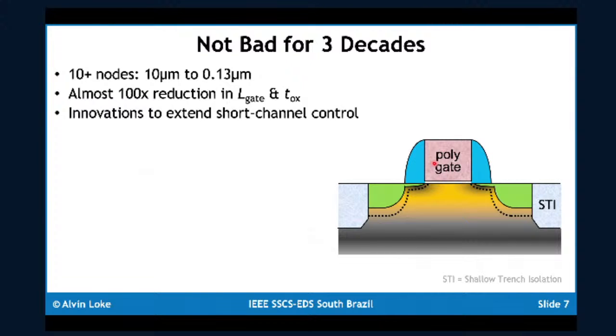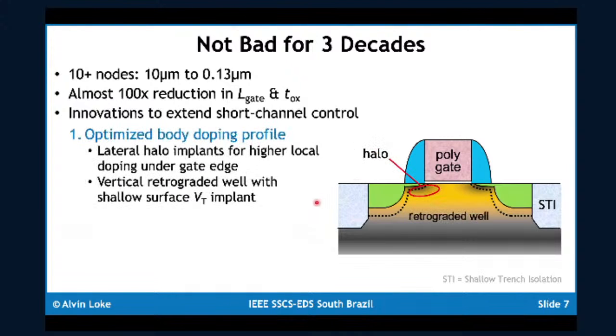Along the way, we've had to introduce several innovations to extend the short channel control. One is extensive body doping profile optimization, where the body doping in both the lateral as well as the vertical direction has been highly tailored, made non-uniform as a result. Halo implants were introduced underneath the edge of the gate to increase the doping concentration there, to reduce the depletion region thicknesses and therefore get you better short channel control.